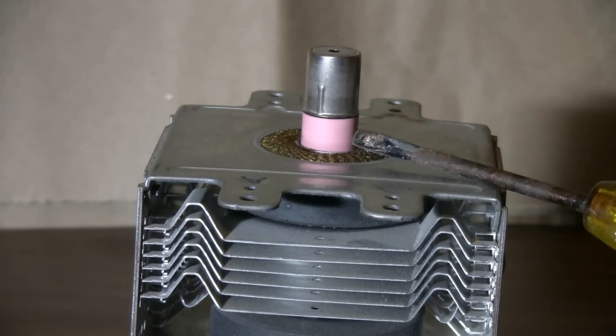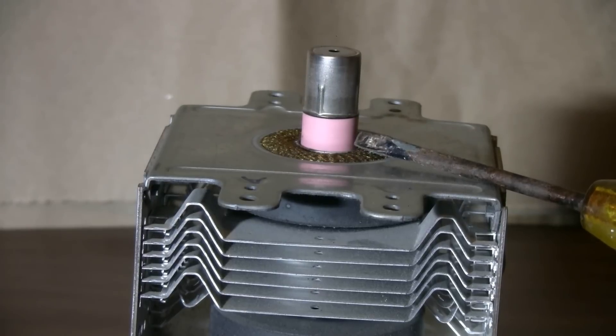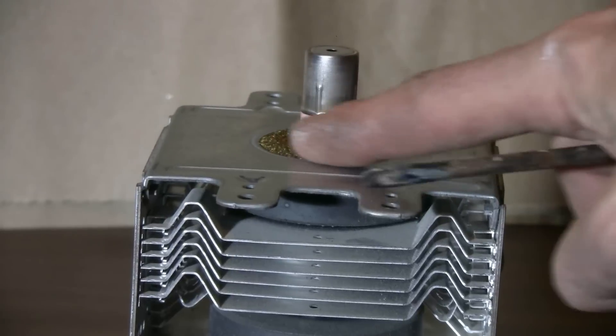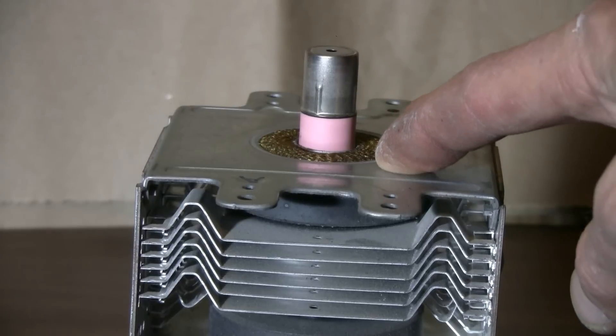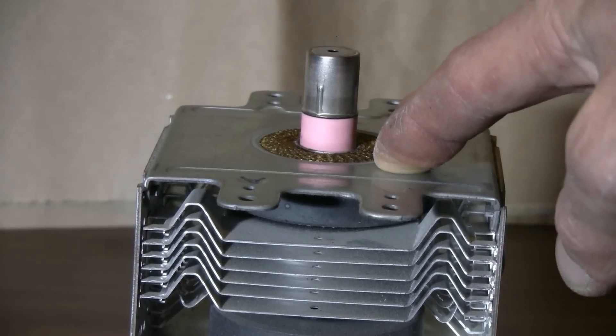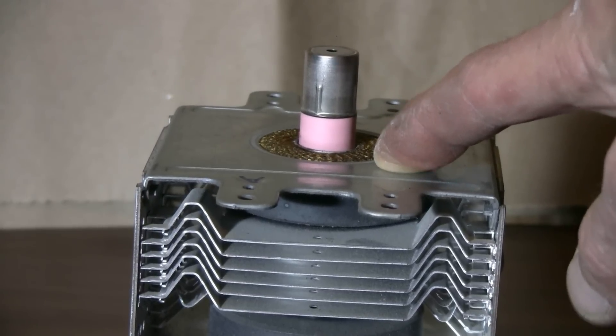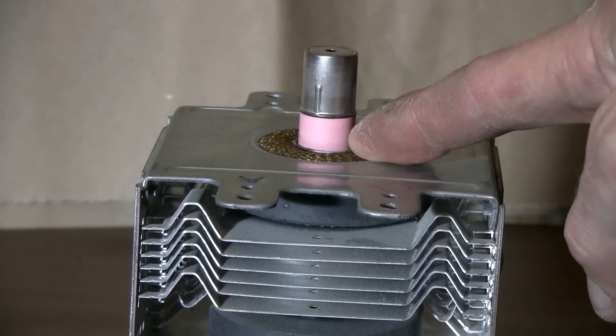It might be aluminum oxide, which is safe, but it could be the quite poisonous beryllium oxide. There's really no way for me to know which kind of insulator I have here. In the case of beryllium oxide, it's quite safe as long as it's whole, but if it gets smashed and dust forms, the dust is quite hazardous if you breathe it. So in taking the magnetron apart, we've got to make sure that we never do anything that can crack or break that insulator.